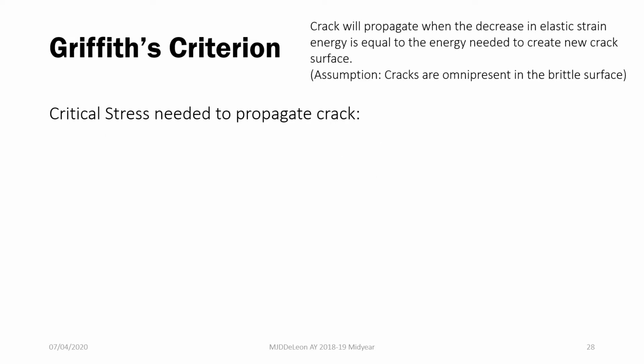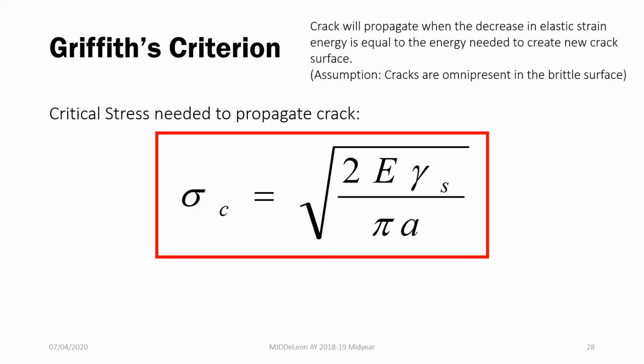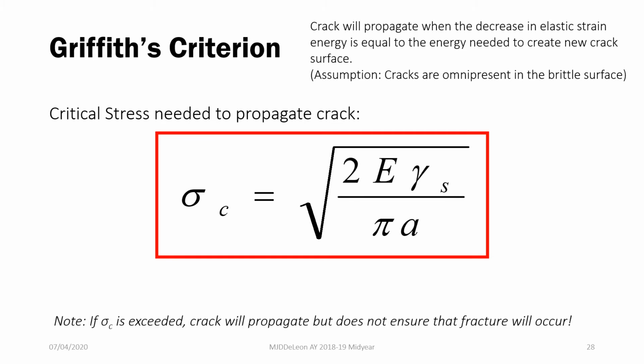Or, parang sinabi niya that your crack would propagate when the decrease in the elastic strain, or yung energy na nirelease natin, is greater than the energy na ginagamit ng material mo to create new surfaces. So the critical stress needed to propagate your crack will be dependent on the elastic modulus of your material and the surface energy of your material. The critical stress for fracture propagation will be equal to the square root of 2 times the elastic modulus times your surface energy over pi a, where a is the length of the crack. So if this critical stress is exceeded, your crack will propagate.